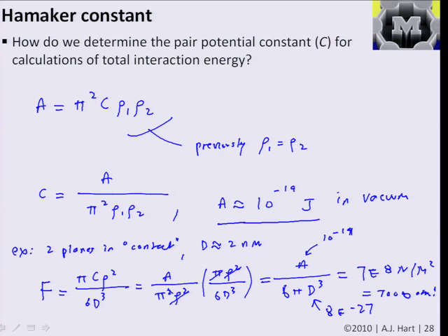But certainly this shows us that the attractive forces between atoms and molecules resulting in macroscopic bodies can be locally very high, and this can have a really practical impact on how nanostructures interact with one another. For example, if you have 2 small pieces of material that are locally very flat, it can take a lot of force relative to the area to pull them apart. So once things become agglomerated together or bundled together, like things like nanotubes, it's really difficult to get them into pieces.